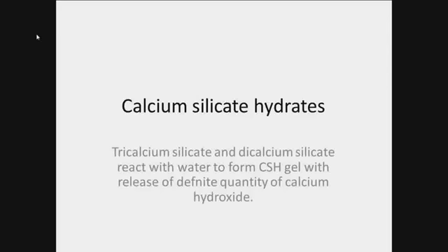It has been observed that the hydration of tricalcium silicate does not take place at a constant rate. Initial rapid release of calcium hydroxide into a solution leaves an outer layer of 10⁻⁶ cm thick of calcium silicate hydrate. After this, for some time, very little reaction takes place. The period of little reaction is called the dormant period. Among the different products, tricalcium silicate is much more reactive as compared to dicalcium silicate and hydrates more easily.